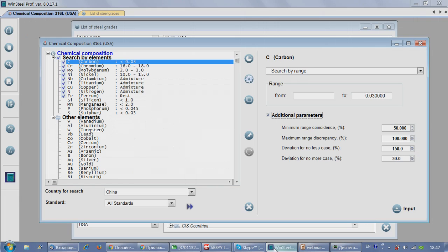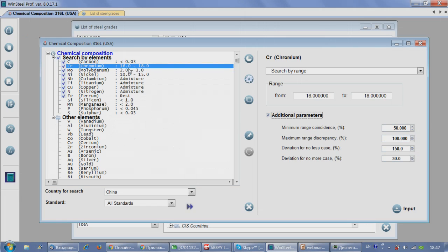And in the software, by default, minimum range coincidence is 50%. What does it mean? This is half of the range of the source grade. I will explain. It is better here not for carbon, but for chromium, for example. The range of chromium is from 16 to 18. So this range is 2%, 18 minus 16. Half of this range is 1%. So if this minimum range coincidence is equal to 50, it will be possible that content of chromium in the equivalent will be from 15, 16 minus 1, to 19, 18 plus 1%. I think you understand.